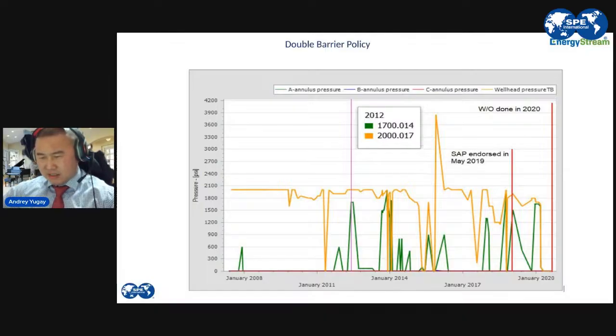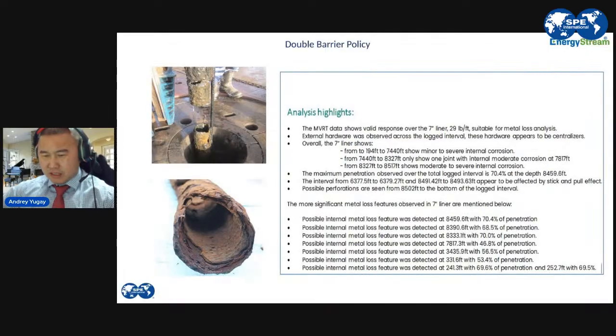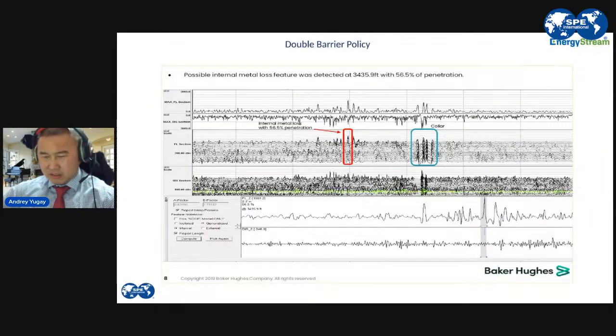Only in 2019 was the well confirmed, investigated, and endorsed for workover, and the workover was done in 2020. So we are talking about 8 or 9 years of exposure of the secondary barrier envelope to pressure and to the well media. And by the way, it was a water injector. So let's look at what happened. During the workover, the tubing was retrieved in pieces. It was severely corroded, just junk. Complete corrosion of the tubing. And the casing, all the way from top to bottom, was severely corroded internally. As you can see, all the way from top to bottom, at different depths. This is an example.